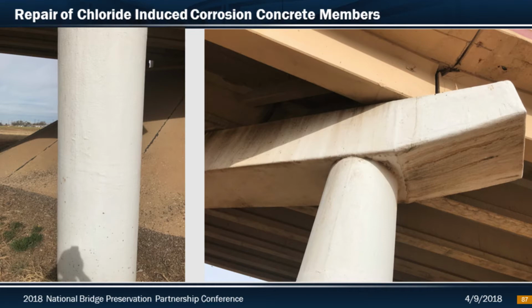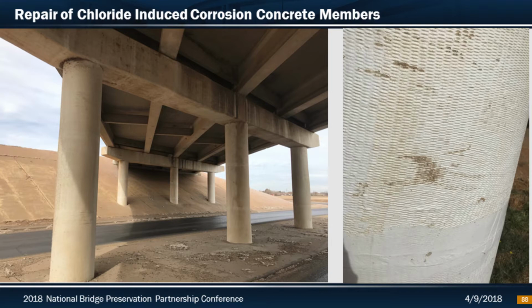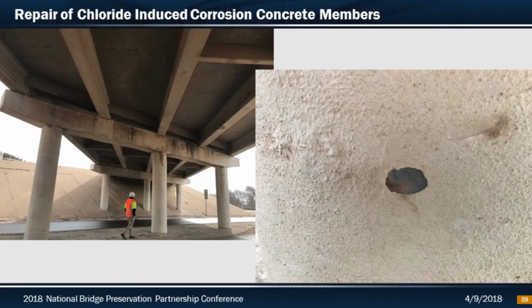Again, the magnitude of the structures was fairly significant, but they appeared to be visually in good shape, again with just some minor staining, minor impacts from vehicles or whatnot. Glass fiber looked to be intact. No significant UV damage was noticed. This is the particular bent line with the carbon fiber wrapping on it. Picture there on the right, you can see where another vehicle impact chipped a little bit of it off. But relatively speaking, no excessive problems with this particular structure.